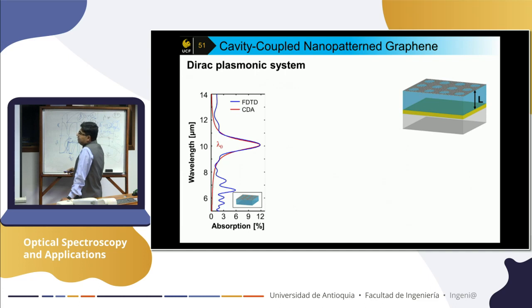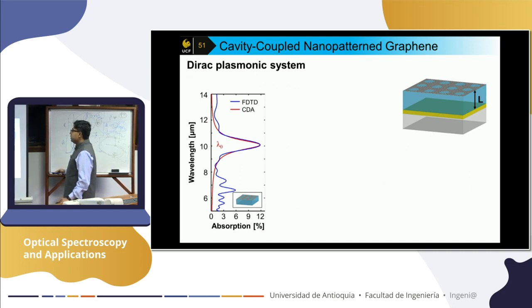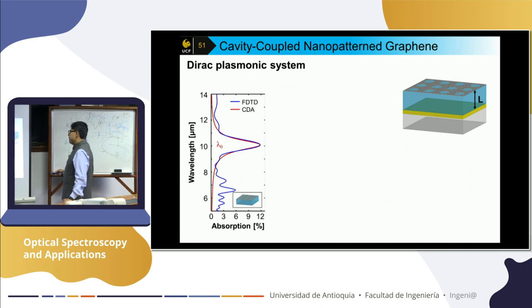We designed for 10 micron because that is the band we are after, the 8 to 12 micron band. That is the infrared imaging band, where infrared light can propagate through the air. This is the band you can use to see people at night, called the night vision band. So our goal is to develop a detector in the 8 to 12 micron band. We designed the pattern so that it absorbs centered at 10 micron wavelength. The bottom line is that you can excite a localized surface plasmon on a nanohole pattern, with about 300 nanometer center to center and each hole 100 nanometer in diameter.